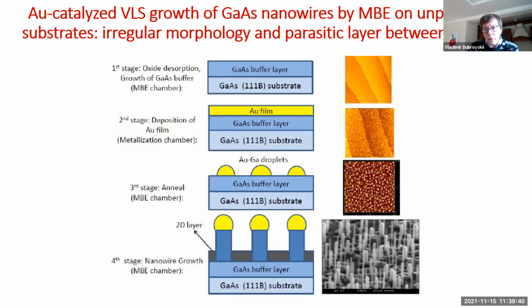So of course, we started growing gallium arsenide nanowires with a gold catalyzed VLS process, where we just deposited a thin layer of gold and then annealed to break the film into an ensemble of droplets on the gallium arsenide 111B surface, and then grew the nanowires, which were quite irregular in terms of their sizes and positions. And we always had this parasitic layer which grew between the nanowires.